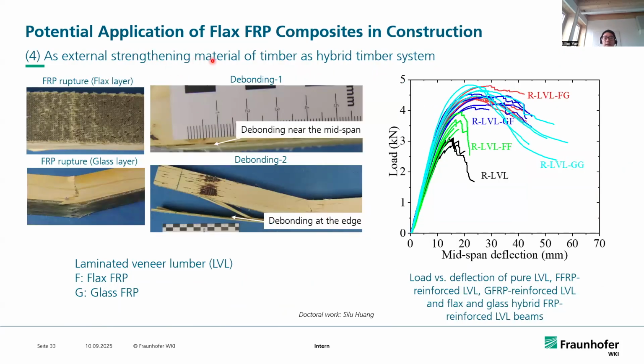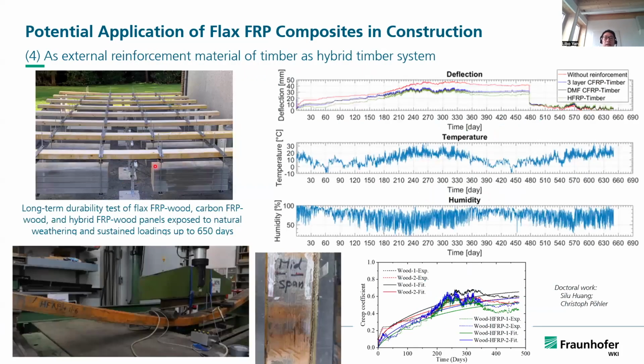And another promising application is the combination of flax FRP with wood to be a hybrid wood system. Here you can see in this load and deflection curve, the use of the flax FRP is able to increase the load carrying capacity of the wood. And in our research group, we also carry out long-term durability tests of full-scale flax FRP wood, carbon FRP wood, and flax glass hybrid FRP wood panels exposed to natural aging and sustained loading up to almost 2 years. Those long-term tests showed promising results of using flax FRP to combine with wood for hybrid system applications.